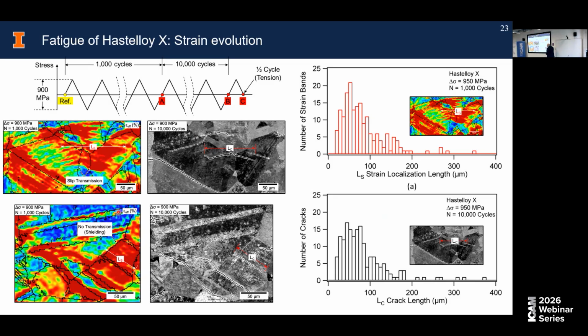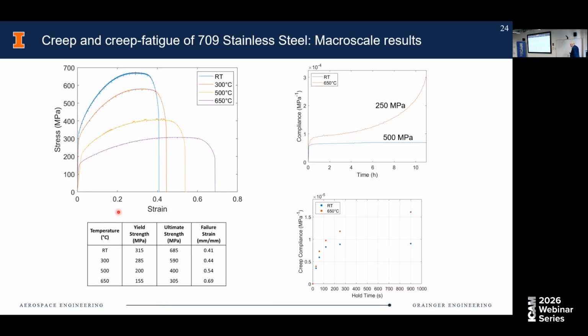In either case, it doesn't matter. Wherever you have a certain length of strain concentration, you have a crack following. Now, I don't know exactly when between these two this happened, in what sequence, but all of these areas cracked. This is a histogram of the strain bands of various lengths, and this is the cracks of various lengths. So this is at 1,000 cycles, and this is at 10,000 cycles. So that seems to be a very good indicator of where cracking will occur.